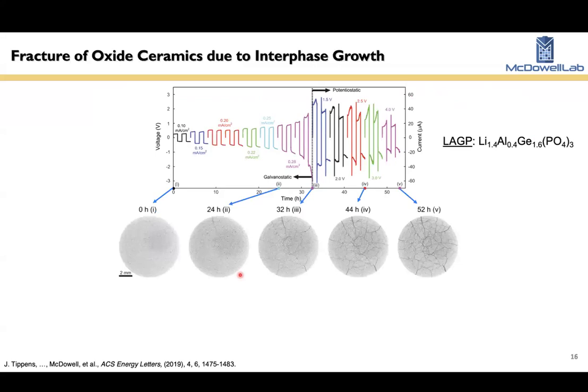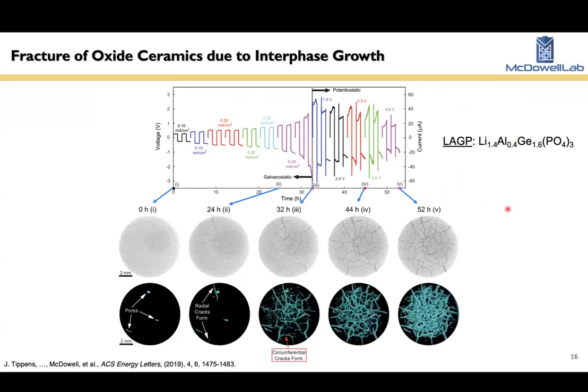Another consequence of interphase formation, and this is back to X-ray imaging, and again in the same solid electrolyte material, is that the interphase formation process itself can cause mechanical damage. So this is, again, back to this idea of chemomechanics. So this is an X-ray tomography experiment where we ran a symmetric cell with an oxide solid electrolyte for many hours, charge and discharge. And over time, we see that this interphase builds up and forms. It grows on the surface between the lithium and the solid electrolyte.